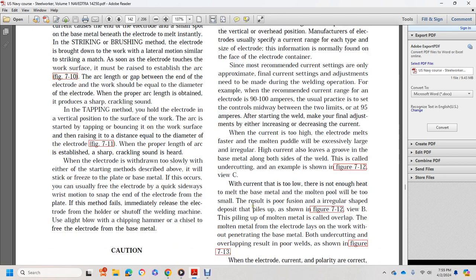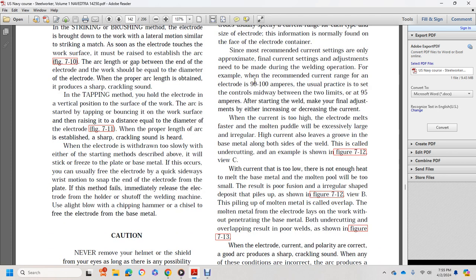When the current is too low, there is not enough heat to melt the base metal, and the molten pool will be too small, resulting in poor fusion and an irregular-shaped deposit with the metal piling up, as shown in figure 7-12, view B. Piling up of the molten metal is called overlap, where the molten metal from the electrode lays on the work without penetrating the base metal. Both undercutting and overlapping result in poor welds, as shown in figure 7-13.